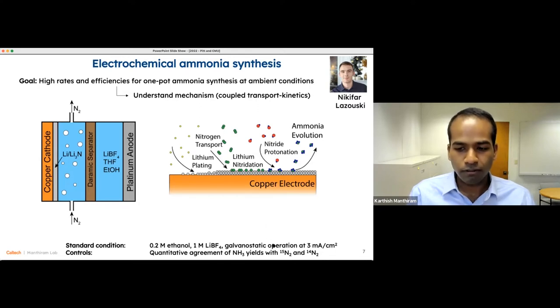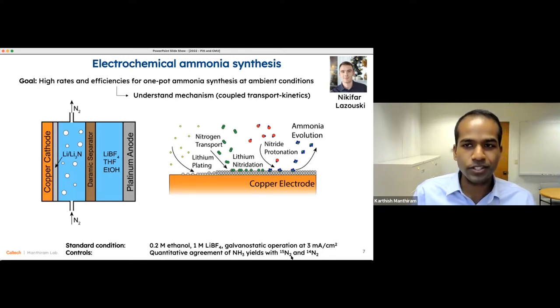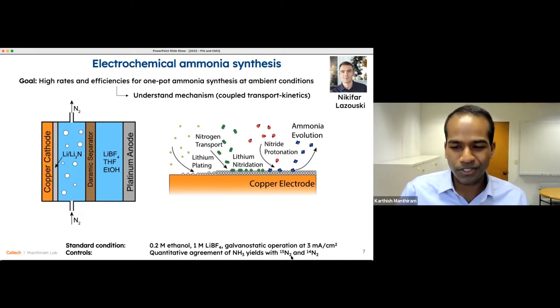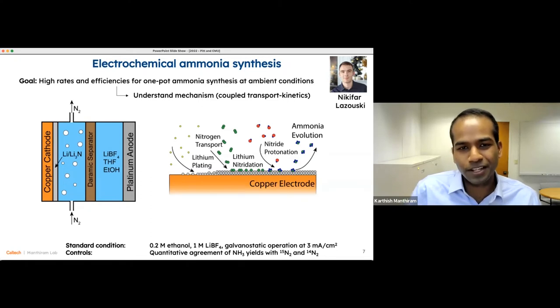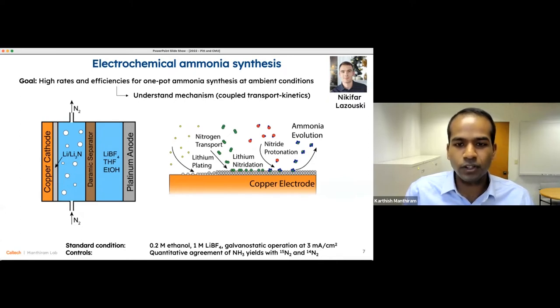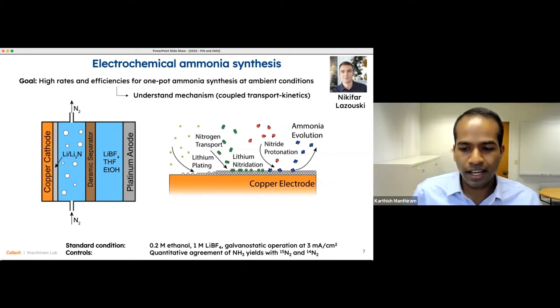We've also confirmed that these yields do in fact come from dinitrogen. There's a whole slew of papers out there that apparently generate their ammonia from nitrate and nitride and from other impurities that are present. So it's really important to do the isotope-based confirmation. Here we see quantitative agreement of the ammonia yields, irrespective of whether we use N15 or N14, and using NMR to see that the yields do in fact arise from the labeled nitrogen.